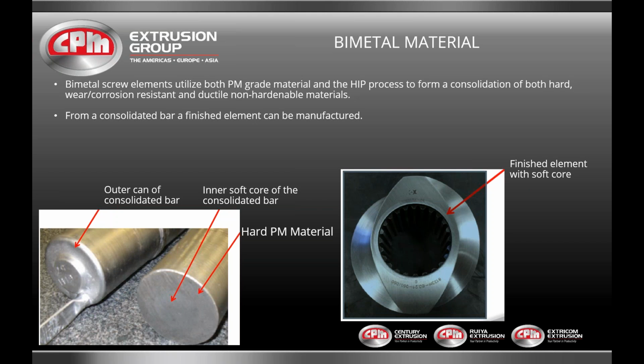We've done some tensile testing on our metallurgical consolidations, where we made the tensile test bars according to the standards, pulled them apart, and the 1018 or the soft core will actually break before the bond breaks. We've never had any separate.